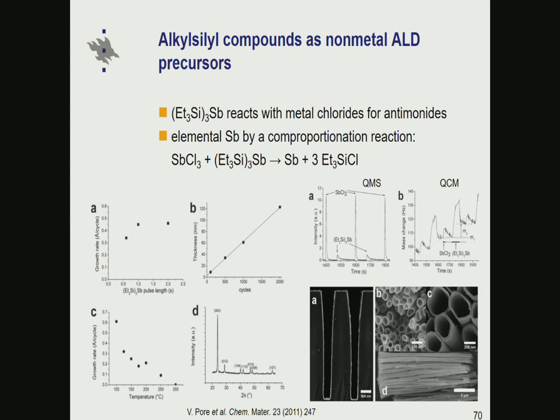But quite interestingly, this also opened a possibility for a very unique elemental ALD process. By choosing antimony chloride and this triethyl antimony compound, there was a reaction that can be classified as a comproportionation reaction, which resulted in deposition of elemental antimony in a very conformal manner through the elimination of triethyl silicon chloride as a byproduct.